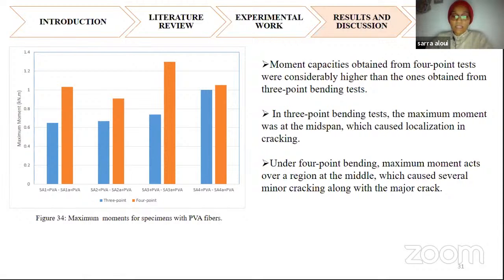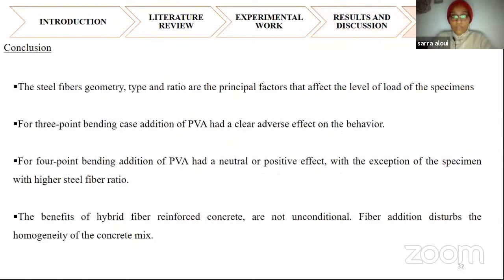But generally we can say that in the 3-point bending test, the maximum moment is at midspan, which caused localization in the cracking. But for the 4-point bending test, the maximum moment acts over a region at the middle, which causes several minor cracks along with a major crack. Now I'm passing to the conclusion.